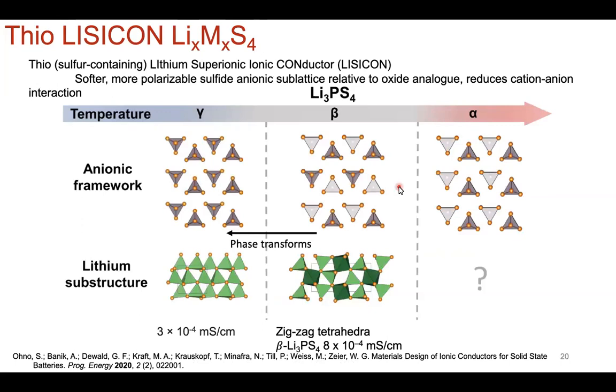So those are LISICON and NASICON. We move now to Thio-LISICONs. And so the last few years have shown a lot of explosive growth when it comes to really exploring the phase space of these compounds. Particularly starting off with Li3PS4. So it's reminiscent of the parent compound that we just talked about, Li3PO4, where the sulfides now replace the oxide. So it's a different anion. The softer, more polarizable sulfide anions really enable the lithium ions to move through the lattice faster.